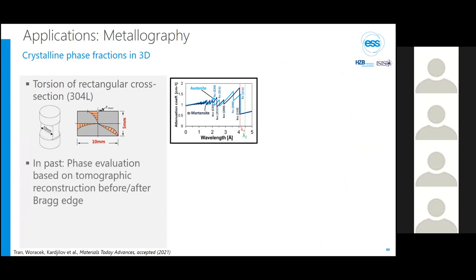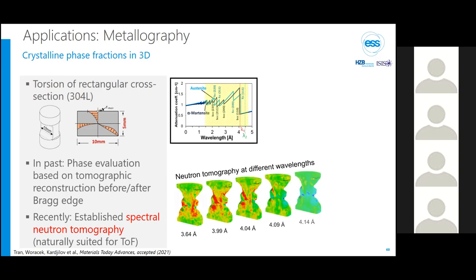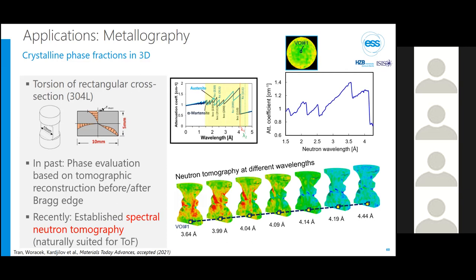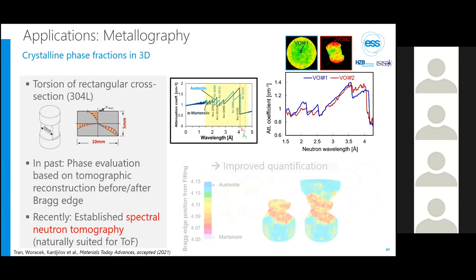As I said before, so far this evolution was based on the ratio of the attenuation coefficient before and after the Bragg edge. But more recently, we and also other colleagues have established spectral neutron tomography for such studies, where tomographic reconstructions are done for a series of wavelengths. So you end up with a four-dimensional data set. This now allows you to plot the wavelength-dependent attenuation coefficients for every voxel. Here, one where the sample is fully austenitic, and here's another voxel where significant martensitic transformation has occurred. What is now really cool about this is that we can perform the fitting of these Bragg edges on a voxel-by-voxel basis and then obtain an improved quantification of the phase fractions than previously possible.